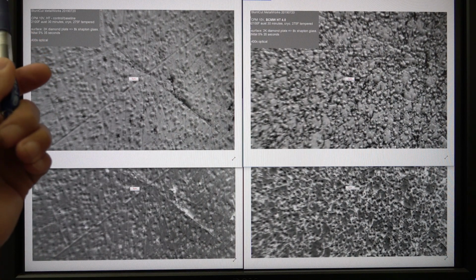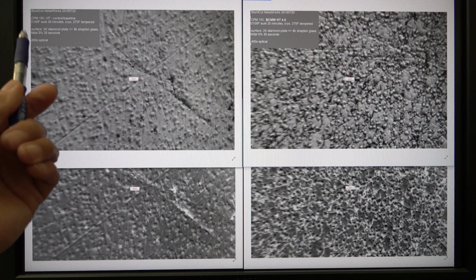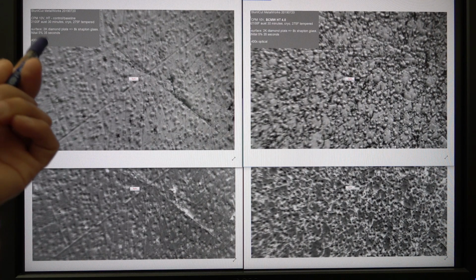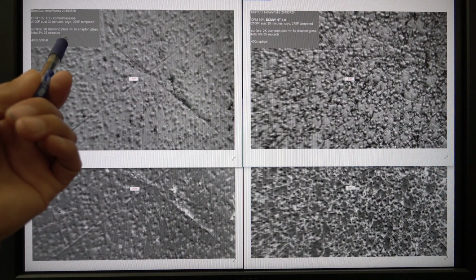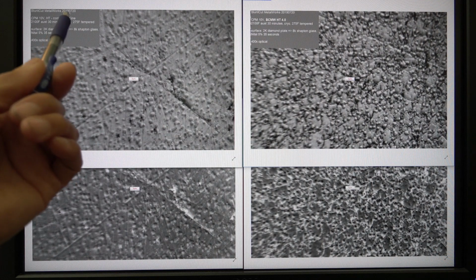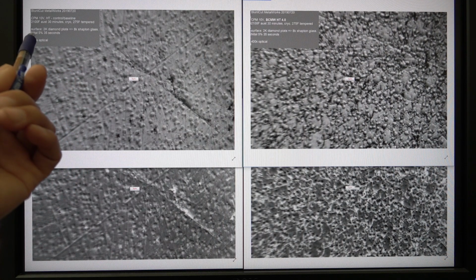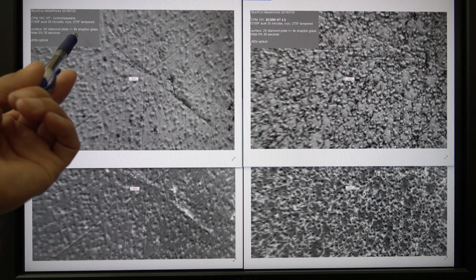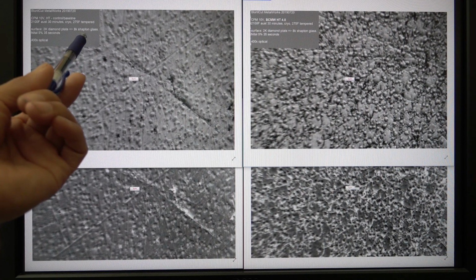I will show you the sample. They all got heat treated, austenitized at the same temperature, which is 2100 degrees for 30 minutes, and they all received a cryogenic or liquid nitrogen soak and were tempered at their peak hardness, in this case 275 degrees Fahrenheit. And to repeat, the surface was flattened with a 2K diamond plate, then lapped and rubbed with 8K sapphire glass, and all etched with Nital 5% for 35 seconds.